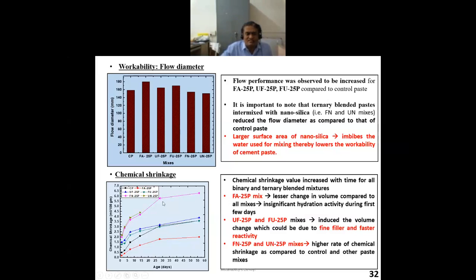Now chemical shrinkage values are expressed in milliliter per 100 gram. Normally we express them with respect to age. Now you can see here, the shrinkage for a fly ash mix is the lowest, whereas for a nanoparticle mix it's the highest. As I was telling you, this is one of the disadvantages. The moment you go for addition of nanoparticles, your shrinkage is going to be more.